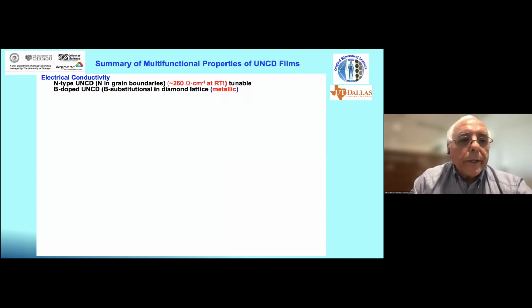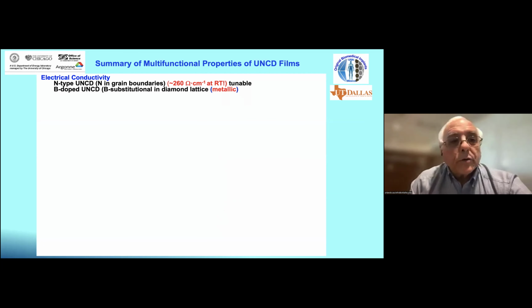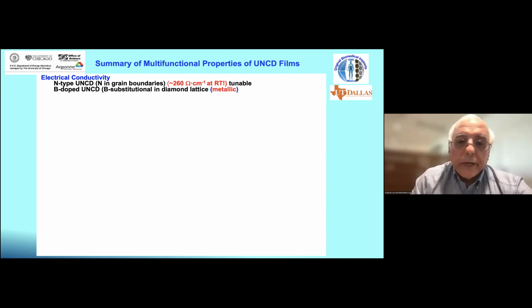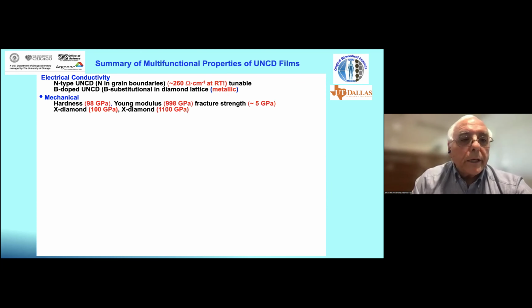So with nitrogen in the grain boundaries, we have semi-metallic conductivity, and this is not doping. Nitrogen cannot replace carbon atom in the diamond because it's too deep, 1.75 eV. So the nitrogen gets into the grain boundary, attached to carbon bonds, and provides electron. On the other hand, we demonstrated that with boron, we can do true doping, where boron can replace carbon atoms and provide electrons to the conduction band, and with that, we have very good metallic UNCD films.